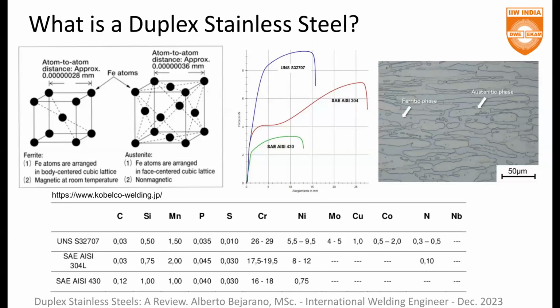in the middle of the screen, in green, the green line represents a typical ferritic stainless steel. It has good properties, for instance, in terms of stress corrosion cracking. It is ferromagnetic, but its resistance is not the best. The elongation is lower than the red line, which represents a 304 stainless steel, one of the most well-known stainless steels that we use.